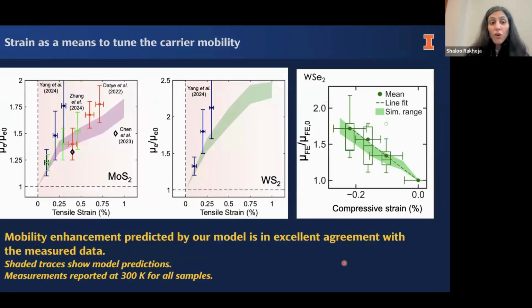All right, so let me also show you how our results match up to the measurements. We can see this range over here. The pink range is predicted by our models, and the symbols with their error bars represent the experimental investigations, some coming out of UIUC, some coming out of other places. And we can see that our model really captures the range of the mobility enhancement across MoS2 and WS2 very nicely.